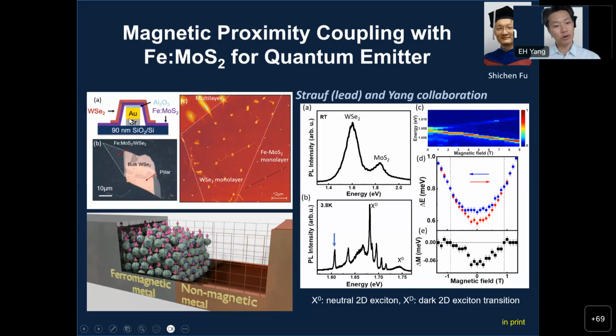So we have this gold chromium pillar, which gives strain into the material. It is basically a stressor that enhances quantum emission. But let's not go there. That's not the focus of this presentation. So we have this iron doped molybdenum sulfide. On top we put tungsten diselenide, which is not a ferromagnetic material, but is another TMD. This tungsten diselenide is the quantum emitter.